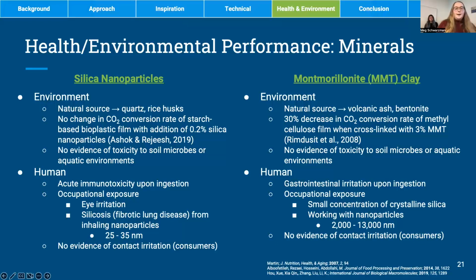On the human health side, we do have a bit of concern in terms of occupational exposure from inhaling nanoparticles. The size of the nanoparticles is listed here, 25 to 35 nanometers. And silicosis is a fibrotic lung disease that has been correlated with the inhalation of silica nanoparticles and silica dust. This is considered a very serious occupational exposure, and we were unable to find any studies that really supported the suggestion that PPE would be effective at mitigating that. So that was something that we flagged as a significant concern.